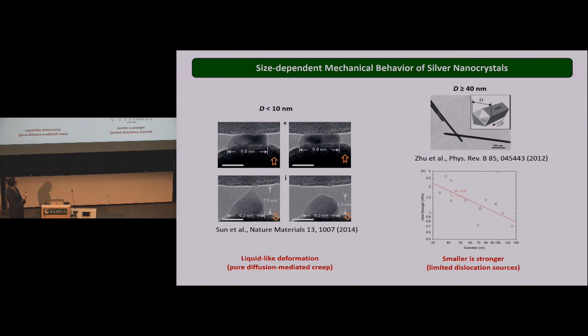When the wires are very small or you have nanoparticles, you start to observe this exotic, liquid-like behavior. The reason is that atoms on the surface diffuse easily and almost represent some sort of melting on the surface, and so they behave more like a liquid. The thing is, between 10 nanometers and 40 nanometers, there was a gap in knowledge. Nobody really tested wires between the two. So the question is, if there is such a dramatic change from strong to liquid-like behavior, maybe somewhere in between, we could have both behaviors matching at a specific diameter. And so what we did is we focused our attention on the mechanical behavior of wires exactly within this range, to see if we could achieve new properties.